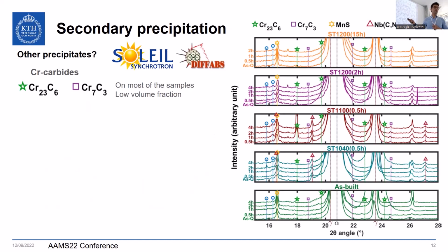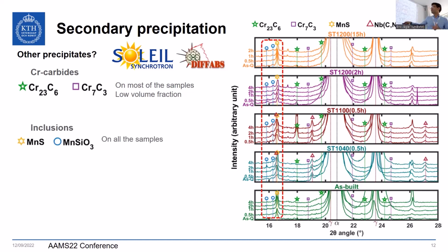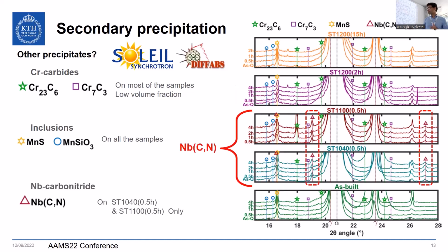We have some chromium carbides. So here I display a lot of data from the Soleil synchrotron on the beamline. So it's XRD data, wide-angle X-ray scattering, for all the different alloys, different solution treatments, and different aging times. So a lot of data, but in short, what we see is that we have some chromium carbides in low volume fraction. We have some inclusions, MnS, MnSiO3, and we also have, more interestingly, some niobium carbonitride, which is present only in these two stages.